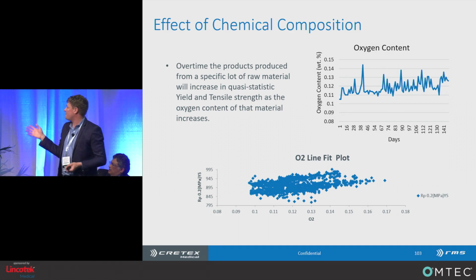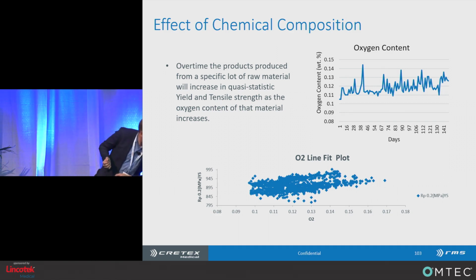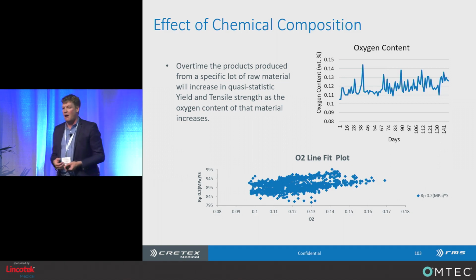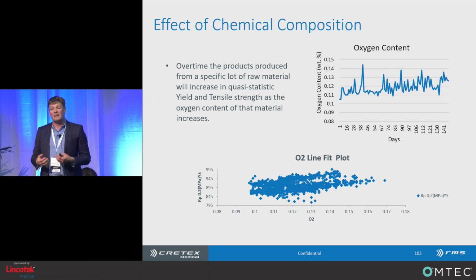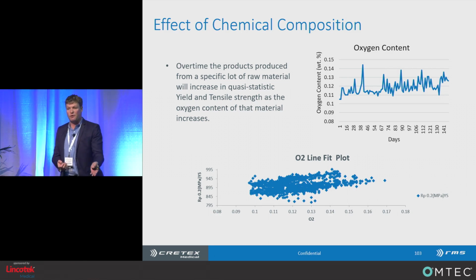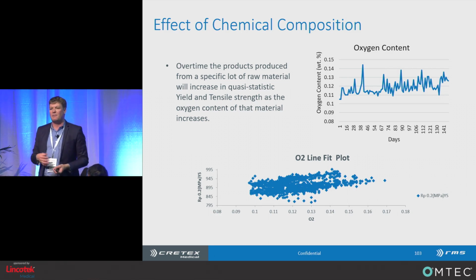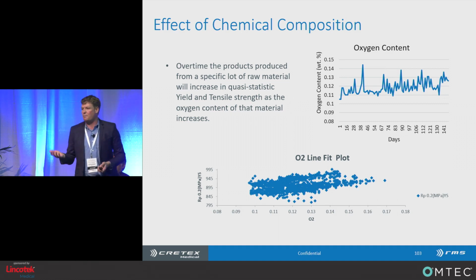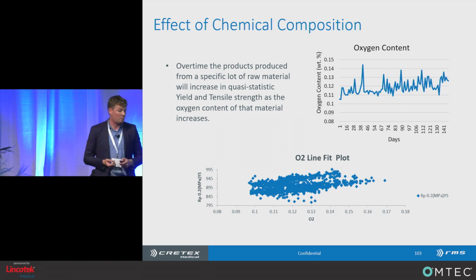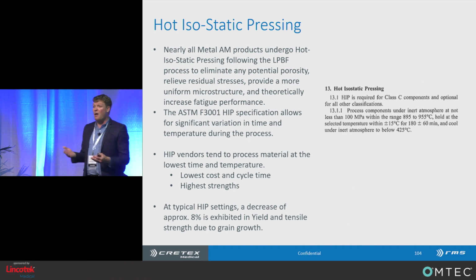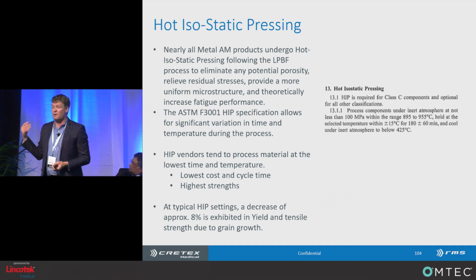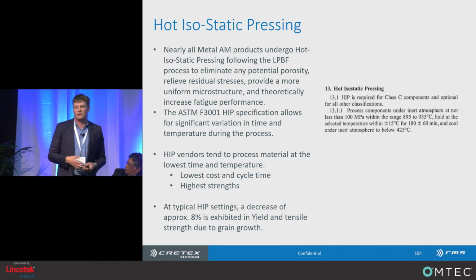So you can see from this graph, let me look real closely here. You can get almost 100 MPa, a 10% difference in yield and tensile strength from the first time you use that powder until the time you decide to retire it, right? So that's a pretty significant change in mechanical properties. Another way that we can manipulate the mechanical properties of additively manufactured Ti-6-4 is through heat treatments.